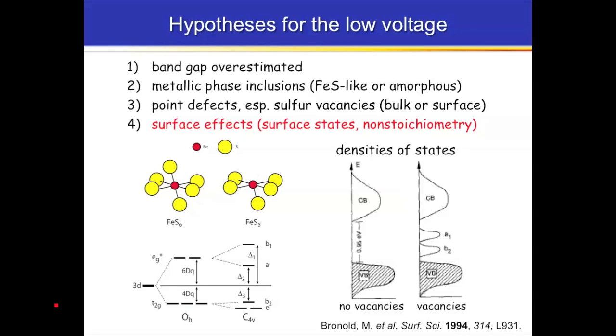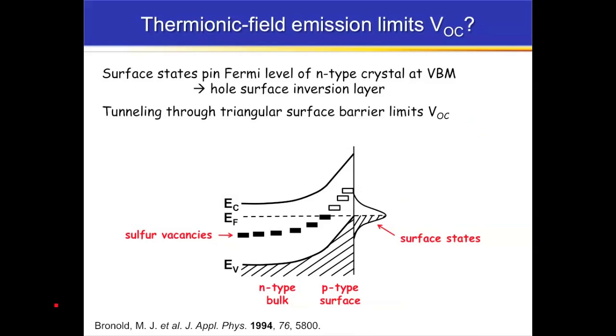work on and we believe the most strongly, is that there's something wrong with pyrite's surface. Either that there are surface states that are causing strange electrostatics at the surface, or the surface is non-stoichiometric and perhaps it's metallic. Okay? So the surface band gap is, for example, 0 or 0.5 volts or something. And this last idea that something's wrong with the surface has some history to it. So this is a paper by Bronold from 1994.